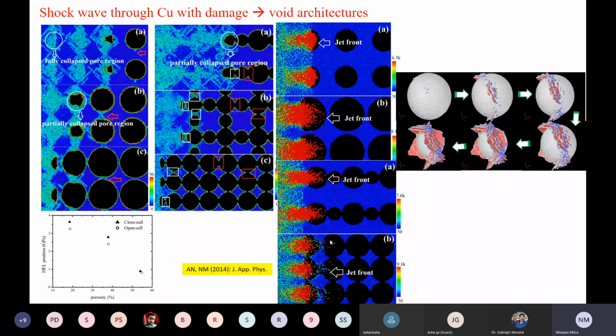As you can see, there are red regions. These red regions are basically hot zones, so the temperature in those regions goes significantly higher. If you can tailor the material by putting in some voids and then improve its properties, then that's a nice thing to do. That's what we have shown in here: if you put in a void, then that will change certain shock characteristics. Obviously, we have done it from the point of view of shock, but it can be done otherwise. Nowadays, people are putting in simulated voids in order to change the material characteristics, meaning, for example, the plasticity behavior of the material. So those things are possible.